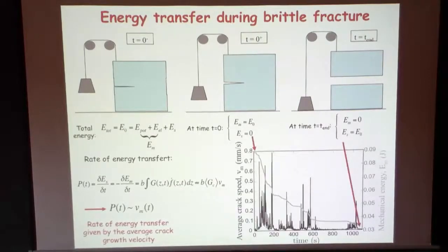Yeah, sure. This GC average is not the same as the one which enters into the equation. In the equation you can write GC as a field of fracture energy that is the sum of your average fracture energy plus some fluctuation that depends on space, and this is this term exactly. Can you... so this is an average over weak and tough regions, whereas your maximum force and maximum resistance is just the average over when the fracture is arrested, which you defined before, so that should be larger.